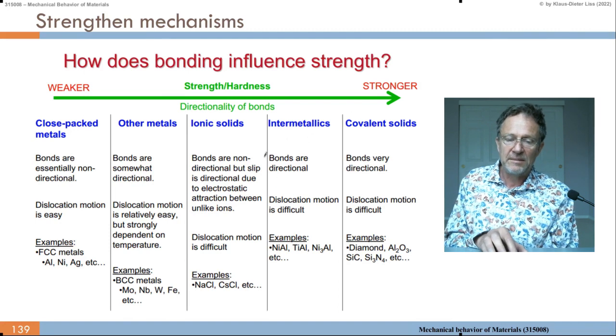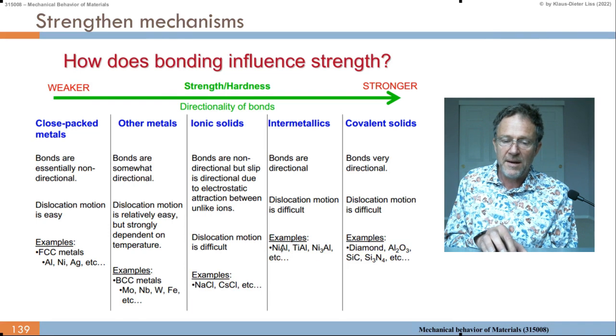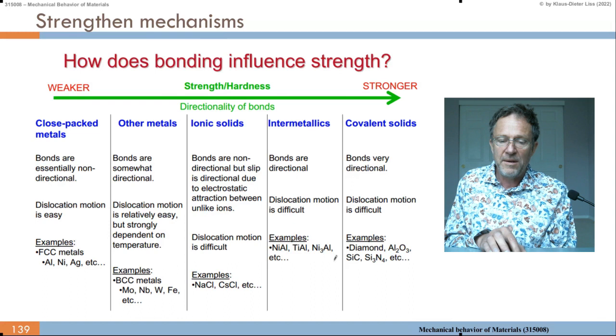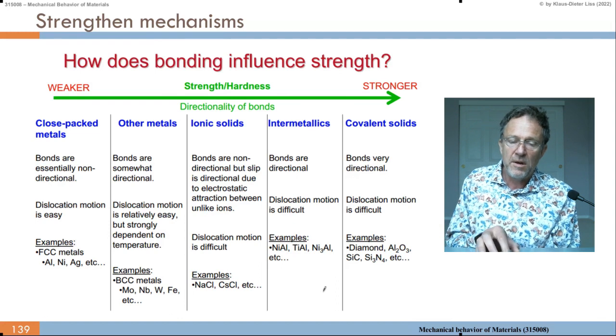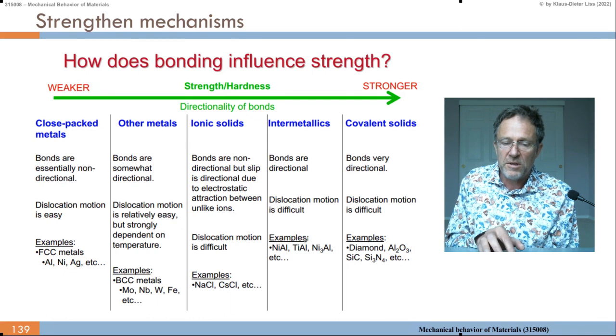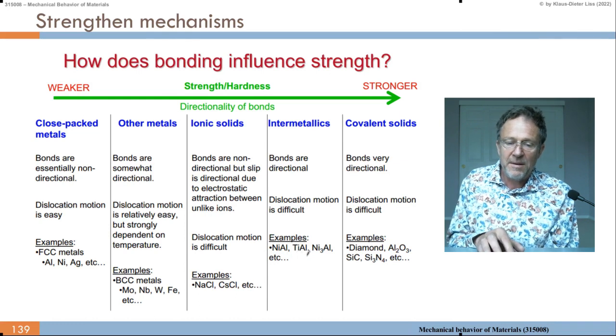Then we have the intermetallics. Titanium aluminide is here, nickel titanium, NiTi shape memory alloy, Ni3Al, Ti3Al, Cu3Au, Au3Cu, and so on. There the dislocation motion is difficult because again we have some directional bonding, we have the order, we have to break this directional bonding, we have to break the order. Especially titanium aluminide: out of the many different stoichiometries of titanium aluminium, there's Ti3Al, there's TiAl, there's TiAl2, there's TiAl3, and so on. So many intermetallics in this system.